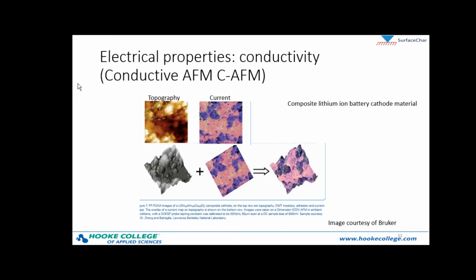In the current image on the right, we see two contrasts, purple and pink contrast. Down here, this current image is overlaid onto the topography, so we have a full visualization of the sample. In the current image, the less conductive purple regions are the lithium cathode material not covered with a polymer binder and conductive additive. The more conductive region in the pink area are areas where the lithium cathode material was covered with this particular binder and conductive additive.